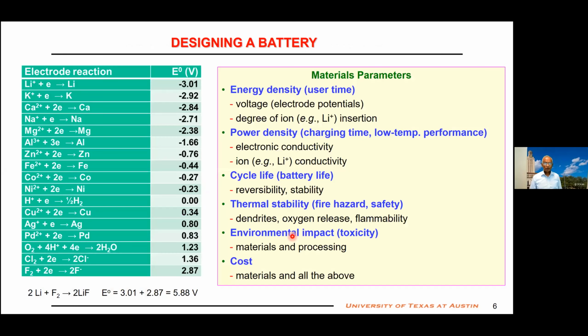Now, those parameters are sensitively controlled by material challenges. So I'll give it quickly here. Energy density depends upon the voltage, that depends, to a first approximation, on the redox potential, although this is in solution, for solids it will be different. Next, how much ion I can store in the form of lithium ion. If it is a sodium ion battery, how much sodium ions I can store. How fast you can charge and discharge depends upon the electronic conductivity of the two electrodes, as well as the ionic conductivity of the two electrodes and the electrolyte.